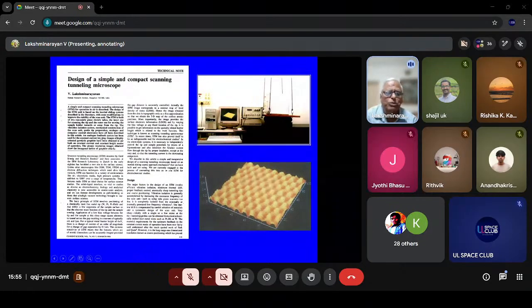Okay, and one way of testing whether this is real or not is to double the distance, and for the same scan rate, you can see double the number of atoms. And see, this is 4 nanometers, this is 2 nanometers, and you can see these variations corresponding to these lines. So this is the one which really sealed the entire thing, because highly oriented pyrolytic graphite is used for calibration purposes of the scanning tunneling microscope. So this was achieved in October 1998, if I remember correctly,